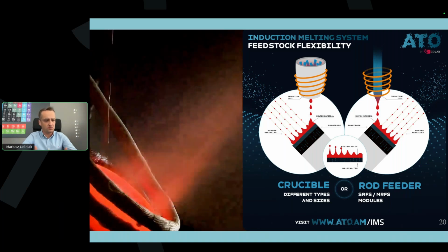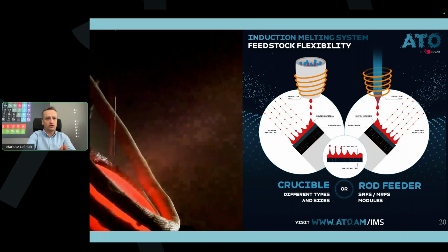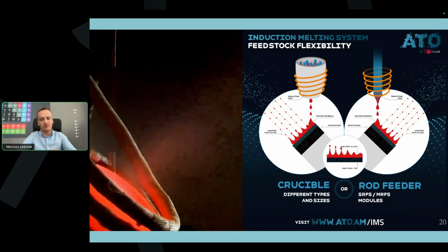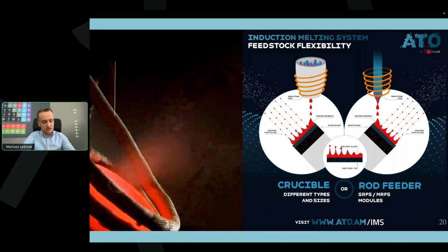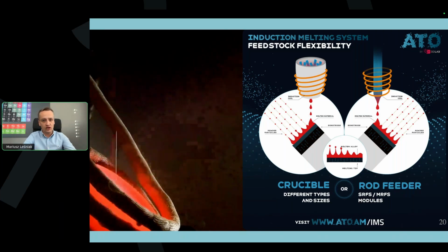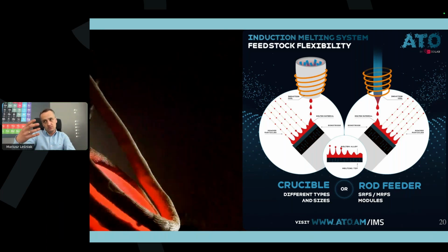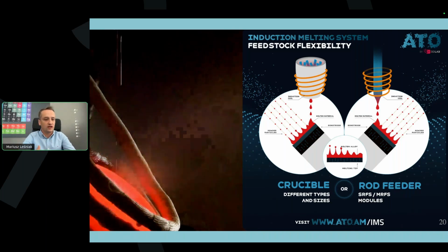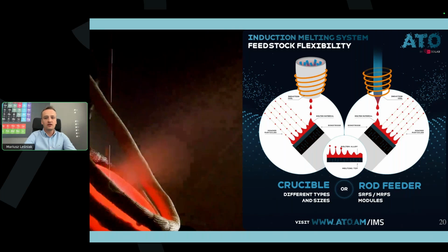But please imagine the situation that maybe someday you would like to use our induction melting system, which is much more gentle for the material, when the risk of the evaporation is also slightly lower compared to the basic module, because we are not using an open fire. You can feed your rod directly to the induction coil whenever you have a risk of cross-contamination from the crucible. The great example is titanium material. It's tricky to atomize titanium from the crucible because it should be a special crucible like a boron nitride crucible, which can be very expensive. At the same time, if you have access to titanium rods, you can feed your rod directly to the induction coil, like the graph I'm showing right now.